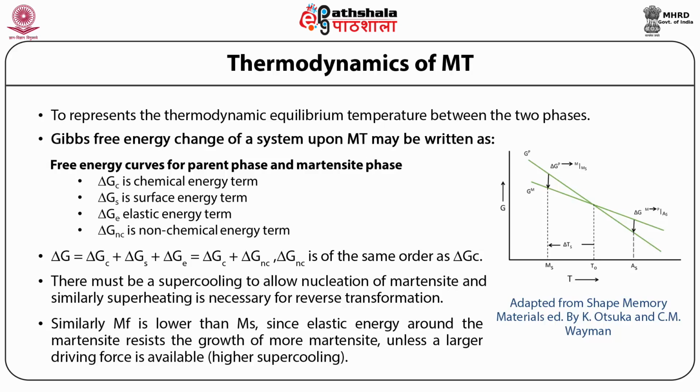Hence, a critical supercooling is required, which is delta Ts, and similarly a critical superheating is necessary before the parent phase can nucleate and start to grow back.